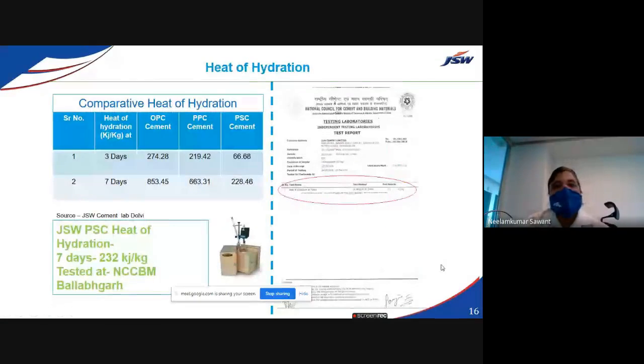Heat of hydration. Somebody may ask how much heat of hydration will be there when I am using OPC as well as PSC or the PPC cement. You can see over here, these are the third-party reports we have done. After 3 days, about 274 kilojoules per kilogram of heat is evolved in pure OPC. If I replace this OPC with fly ash, the heat of hydration is reduced to about 219. And with PSC, it is drastically reduced, down to about 25%.